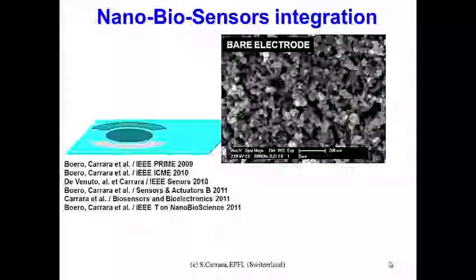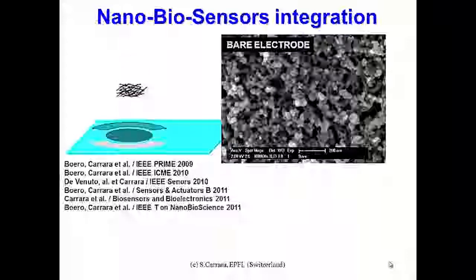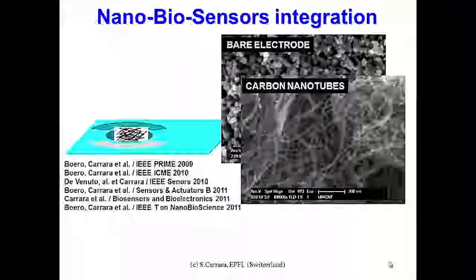Over the years, there have been several experiments demonstrating that we can consider, for example, screen-printed electrodes, typically used for electrochemical detection, including that of glucose. The scanning electron micrograph of this kind of carbon-paste electrode looks like that. And we can simply drop cast carbon nanotubes on top of this electrode, and after the evaporation of the solvent, we obtain this kind of carbon nanotube forest.